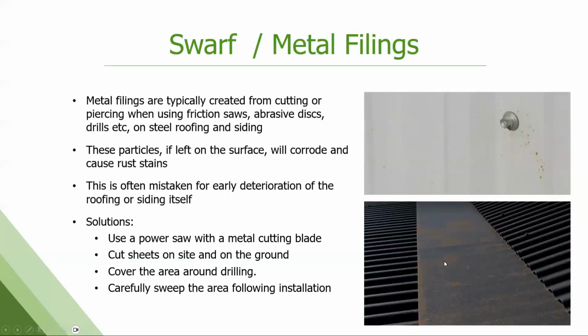Swarf and metal filings, again, these are little shavings of metal from like a screw hole or cutting that don't get cleaned off. Those little metal shavings are now rusting because they're exposed to the environment. This comes into me as, hey, my paint is failing and it just got installed. And then I look at the pictures and I go, nope, those were metal filings that didn't get cleaned off. This staining that happens on the paint surface is really hard to remove. Not a performance issue long term, but definitely an aesthetic issue that most new building owners are not happy with. So we have a lot of tech bulletins around how to cut, how to clean, the best way to prevent this and to get rid of it if it does occur.